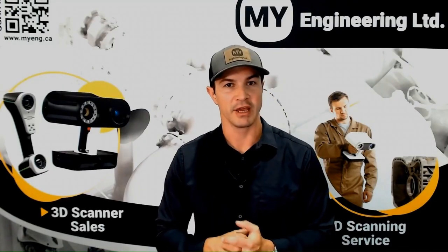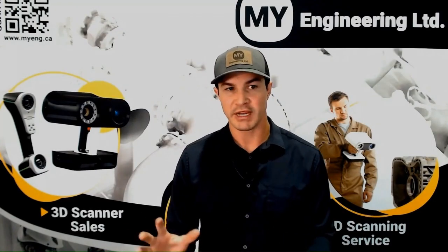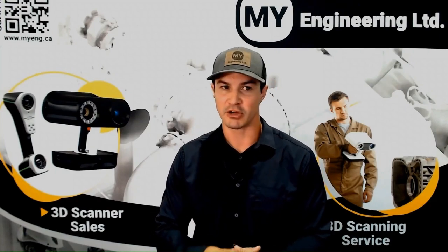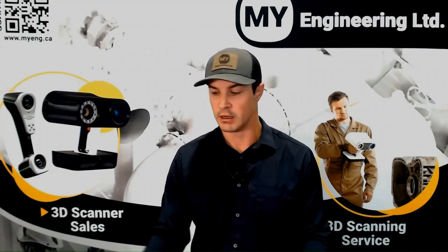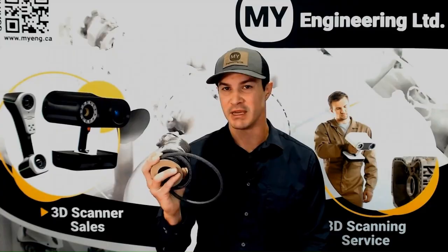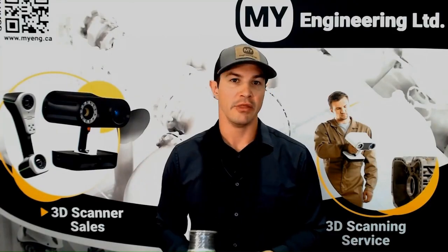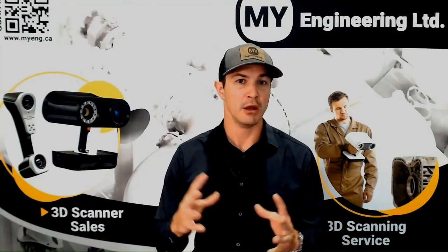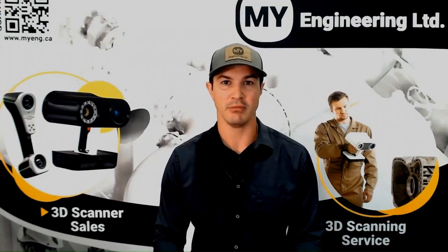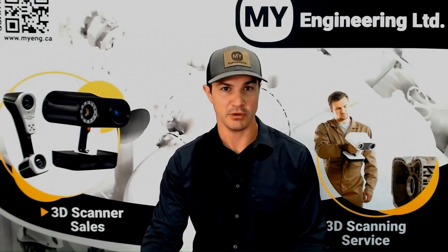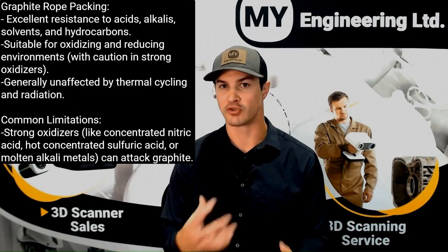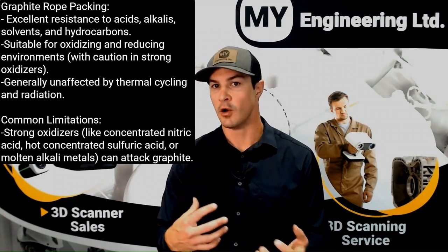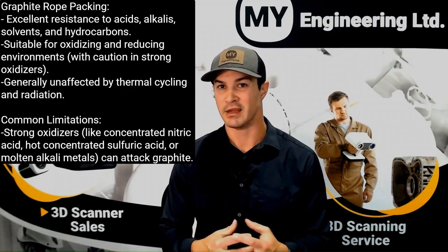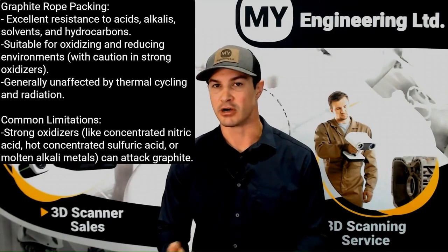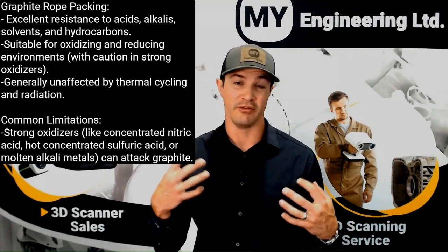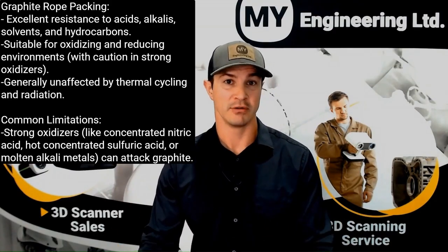So the next thing we're going to look at is chemical compatibility. With this one, I didn't do any testing, but I can tell you a little bit based on my research and experience about what we've seen. So graphite rope packing tends to be a much more inert material than copper tubing. It can be used in most applications, and there's seldom a case where we see that it cannot be used. There are some cases where strong oxidizers like nitric acid or hot concentrated sulfuric acid can attack graphite, but these are exceptions to the rule of graphite being a very inert compound.